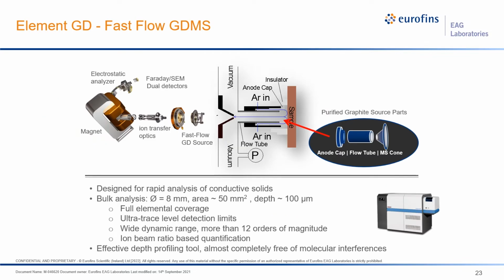The second type of GDMS instrument we have is called Element GD. It is based on a fast flow GD source, and the ions generated go through the ion optics, then through a magnet and the electrostatic analyzer. The detector is different from the previous VG9000: it has Faraday and SEM dual detectors. Here is a blow-up of the fast flow source. You have argon sweeping through the sample surface, sputtering going on, and the extracted ions going out to the ion optics.